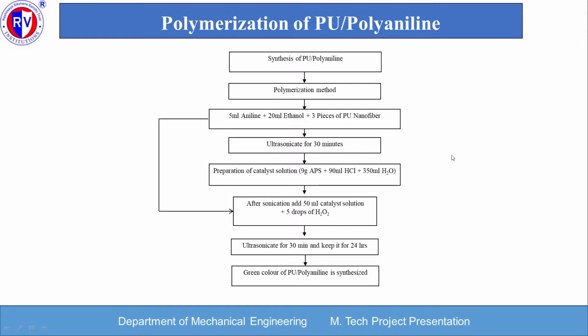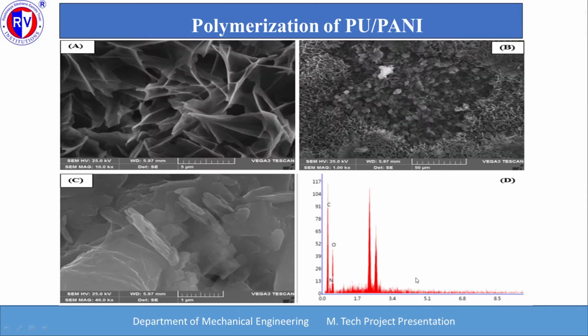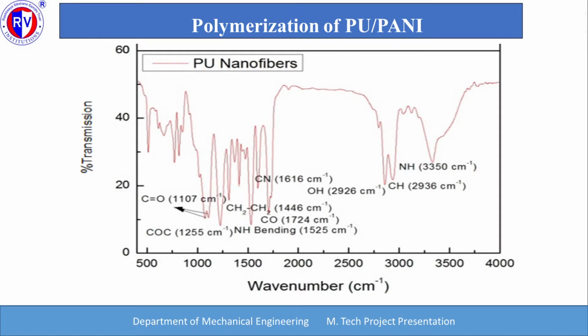The third step of our project is the polymerization of PU and polyaniline. First, this is the procedure we have followed for the PU polyaniline polymerization. And these are the SEM images of the PU and PANI composites. As you can see here, these are very good structures that we have got from the SEM images. And this is the EDAX that shows the presence of carbon, oxygen, and nitrogen. And this is the FTIR of the polymerization of PU and PANI.